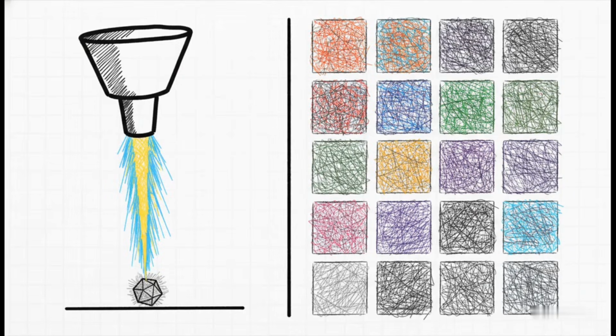Let's look at those first 2 superpowers. FESEM provides a phenomenally bright, highly focused electron beam. This high spatial resolution means you aren't just looking at a big chunk of bulk material. You can literally point that beam at an individual nanoparticle or maybe a tiny 20 nanometer defect and say, hey, what is that specific thing made of? And on top of that, you get simultaneous elemental mapping. As the beam scans across the sample, you're generating beautiful color-coded spatial maps of elements like zinc, oxygen, gold, and silicon right alongside your topographical image.